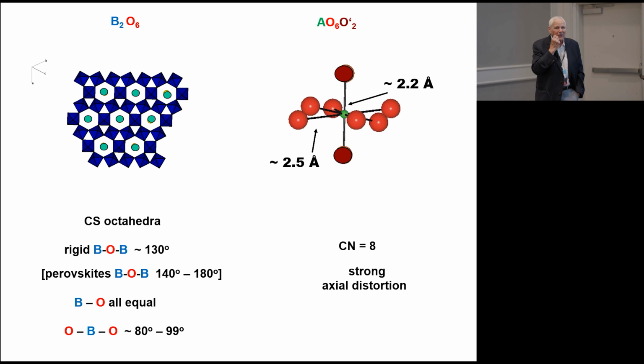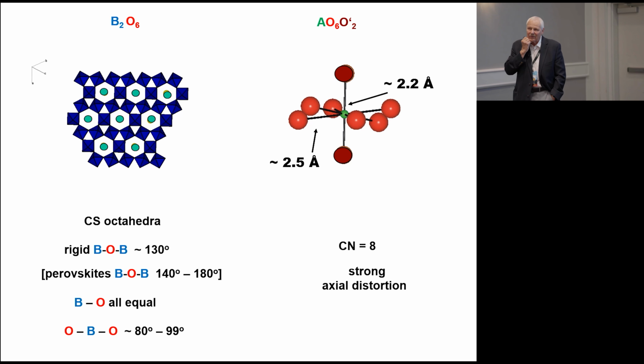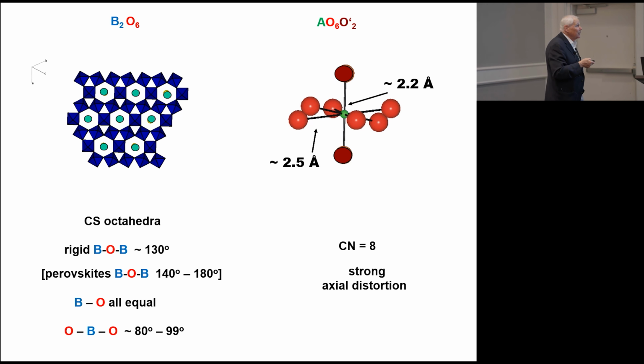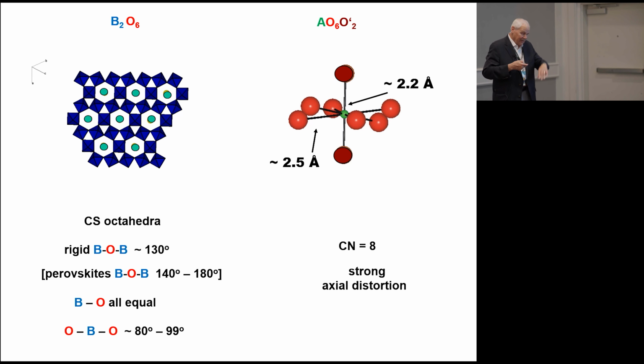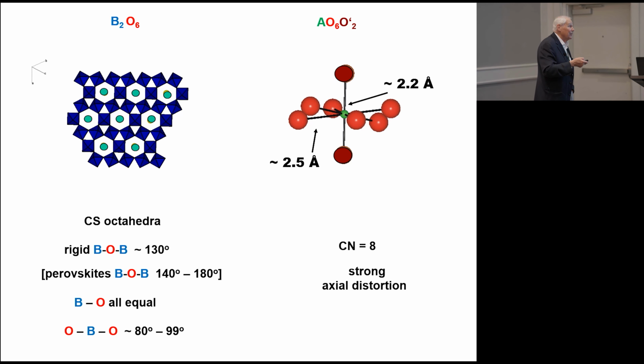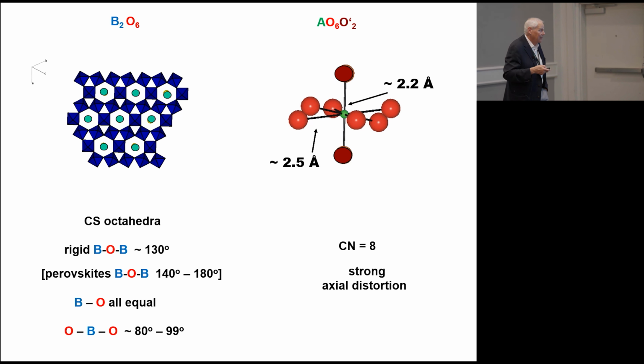And you don't learn a lot by looking at a unit cell representation of the pyrochlore structure. There are 88 atoms in the unit cell, so we'll split things up a bit. There are some similarities with perovskite. The small cation site is octahedrally coordinated, and the octahedra share corners. But they're very constrained. There's not a whole lot of opportunity for tilting, and so there's not a nice space group family tree of things you can get to by tilting octahedra. You don't tilt. And the B-O-B angle is pretty well rigidly held at about 130 degrees, compared to perovskites, in which you have, of course, a wide range of angles.